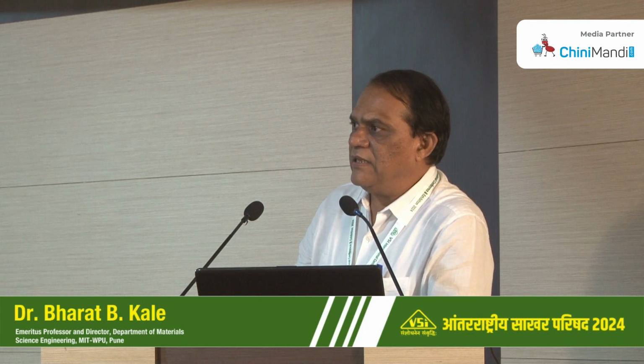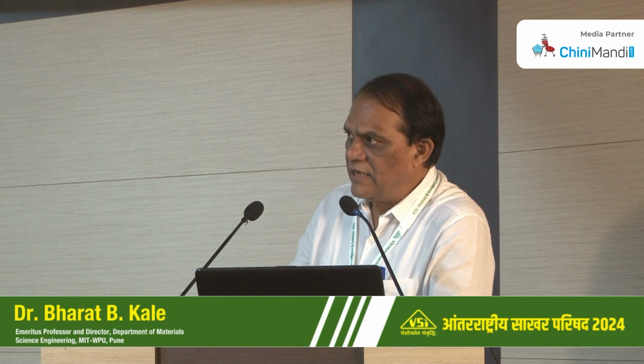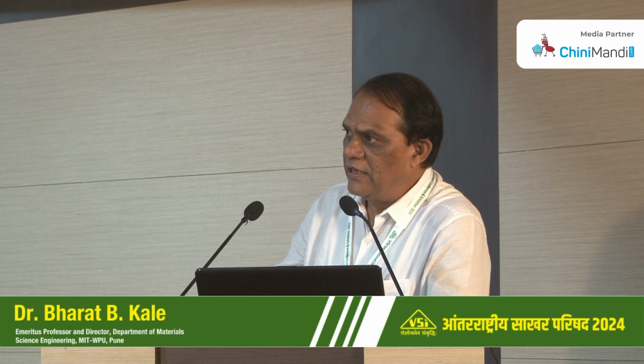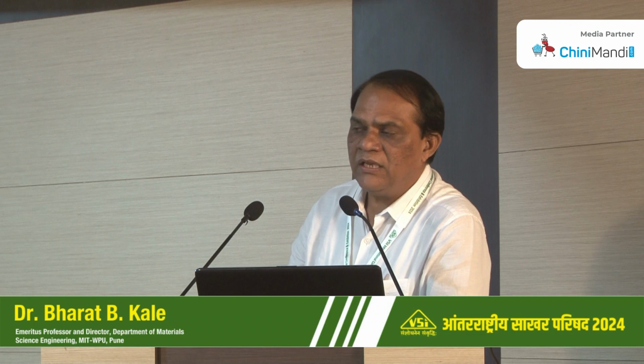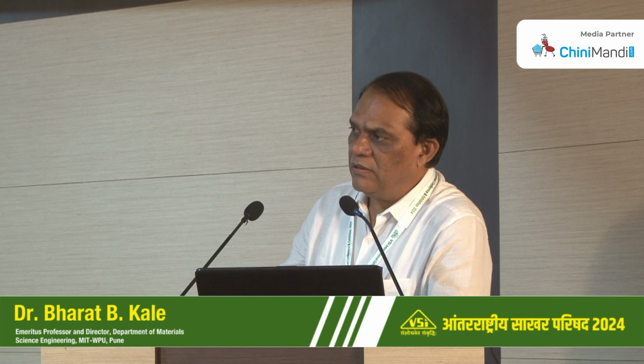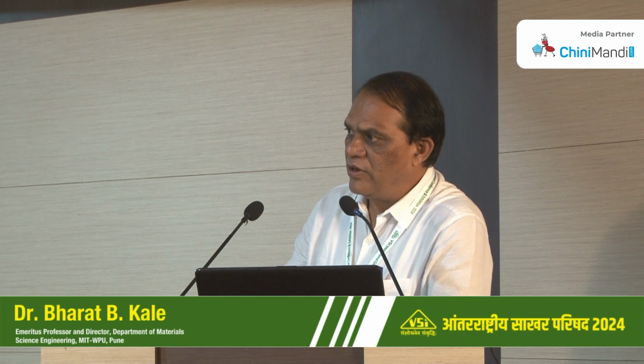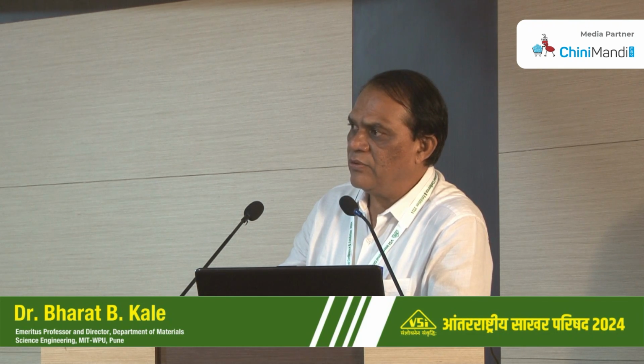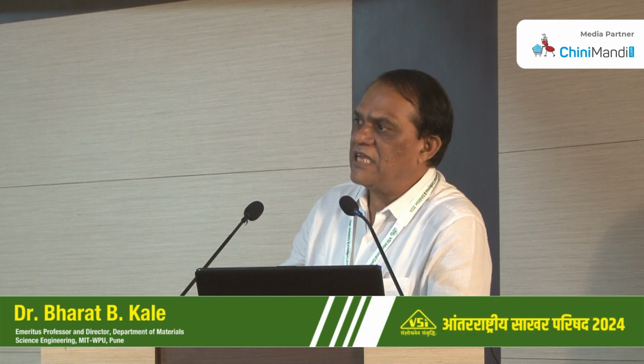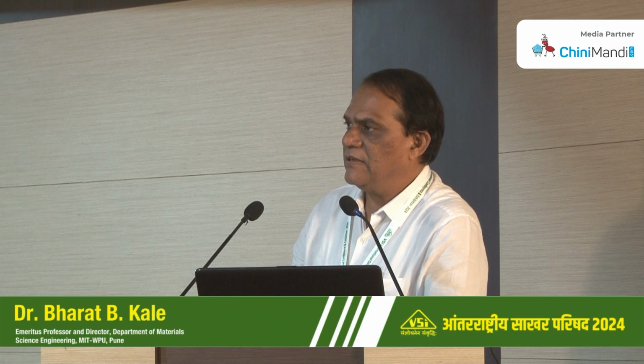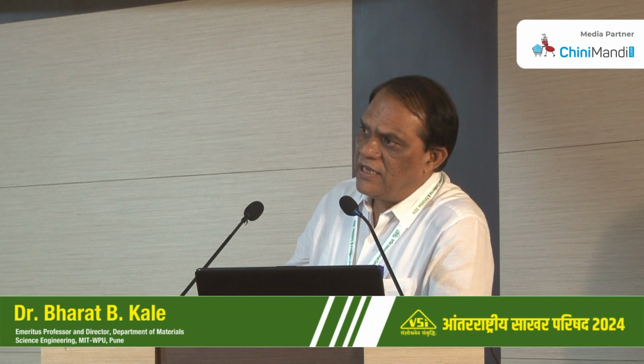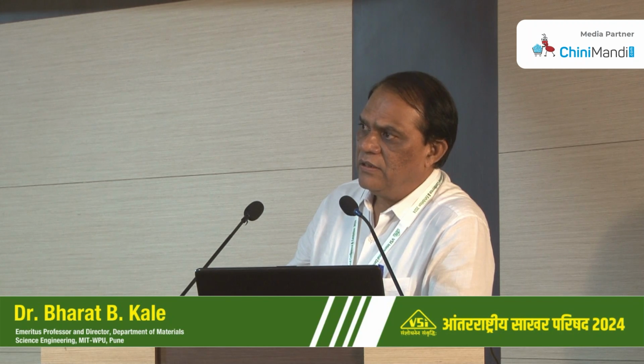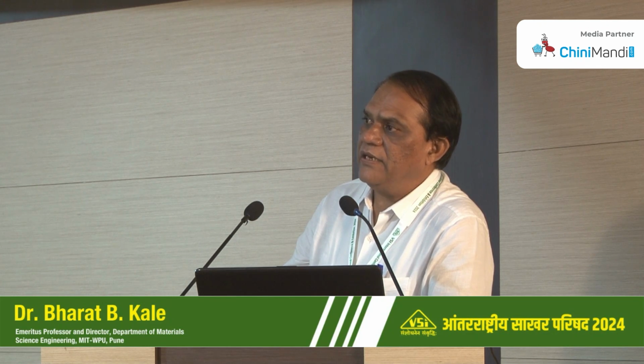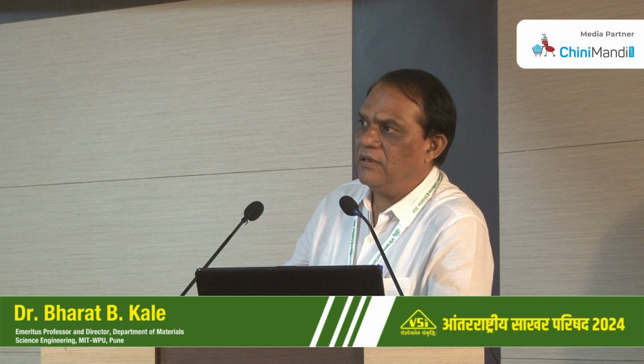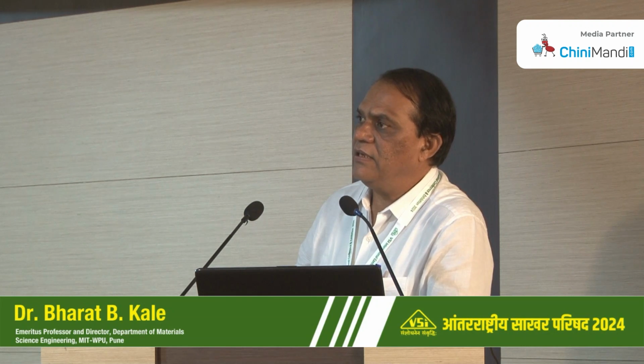Right. So you can see here the cadmium sulfide grown in the glass, and initially it is only 300 nanometer absorption, but it has gone into the visible region when we grow the cadmium sulfide in the glass, from 3.12 electron volt to 2.48 electron volt. So this yellow colored glass powder we can use as a photocatalyst. They are highly dispersed in the glass. If you see the HRTEM, you see that they are highly dispersed. It is only 2.5 nanometer, and they are highly crystalline. If you see the SAED pattern of this glass, they are polycrystalline, as you can see.